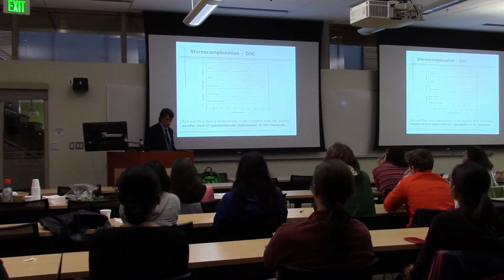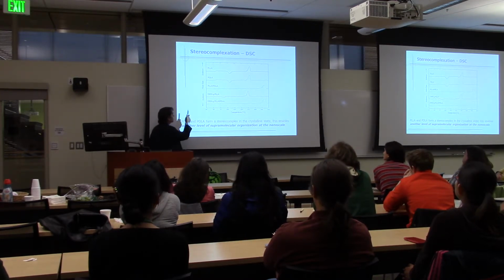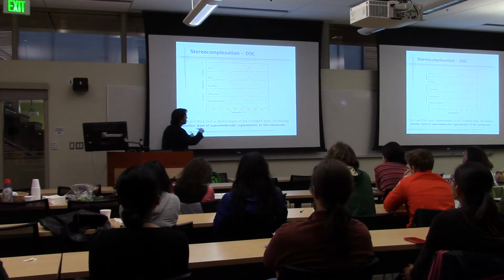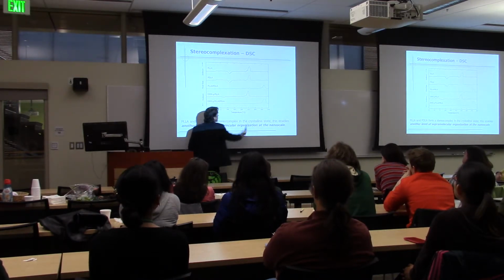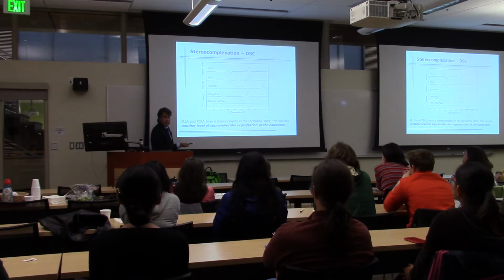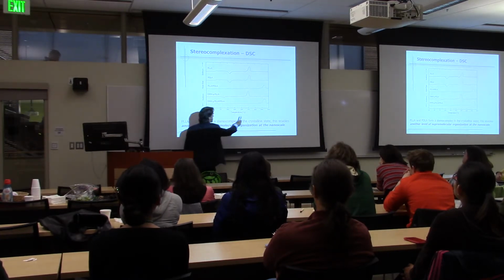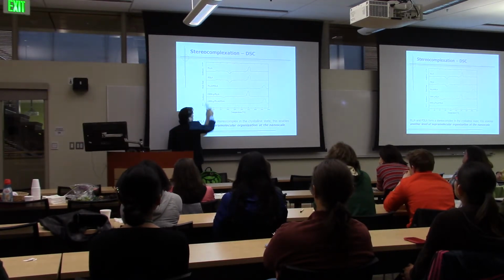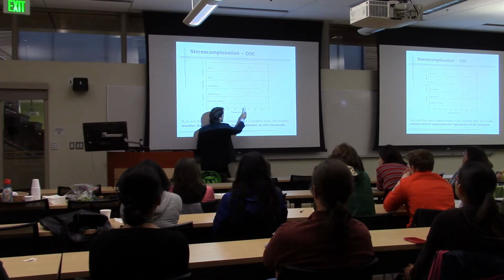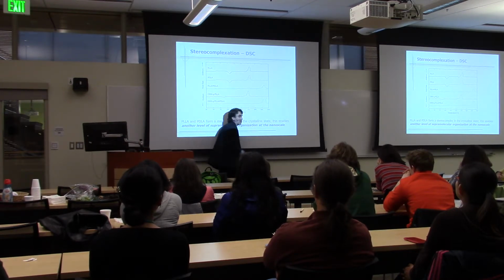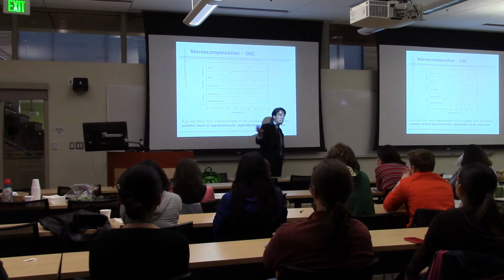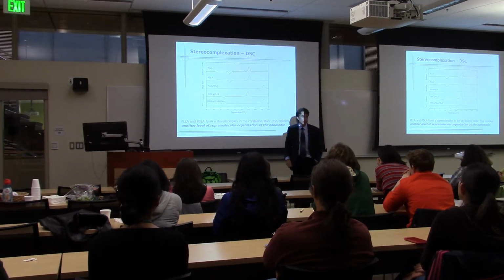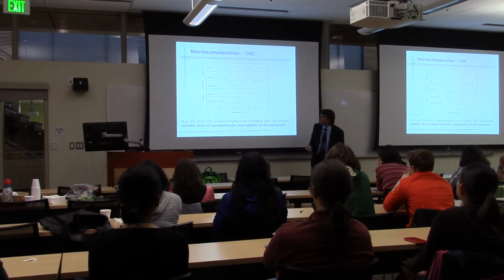Here's an even easier way to understand that. We're just looking at melting points. At the very top we have the all L, and you can see the melting point is around 180 degrees or so. If we make the all D, we again get 180 degrees. But if we mix those two in a 50-50 mixture, we get the stereocomplexation. We didn't get the stoichiometry quite right. There's a little bit of homopolymer melting there at the same 180. But the majority of the melting is taking place up at 230 degrees C. So that's that 50-degree rise in melting temperature that people take advantage of with polylactides.